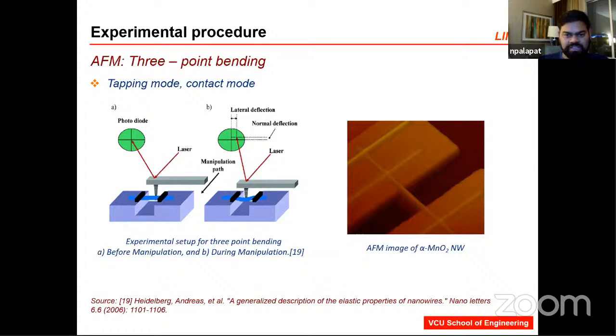So what I did is, as anyone with an AFM will know, contact mode does not give a good image, but it gives good force displacement curves, whereas tapping mode gives really good, beautiful pictures. So I've used tapping mode first to get my image of the nanowire. Then I go into contact mode to exactly insert the force where I need on the nanowire.